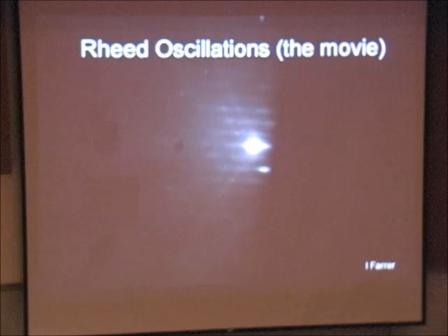Now, this is an example of how one actually looks at the growth process of the molecular beam epitaxy. And here we have what is known as RHEED, reflection high energy electron diffraction. An electron beam is shone at the surface of the epitaxial layer as it is growing. And what happens is, there's quite a strong reflection when we have a complete atomic layer. When we have an incomplete atomic layer, it's essentially diffuse scattering all over the place. So not very much comes back.